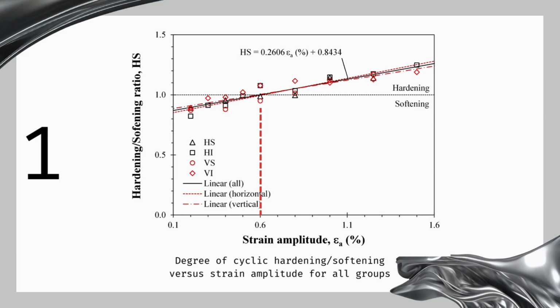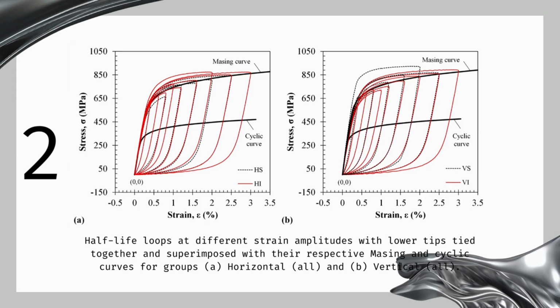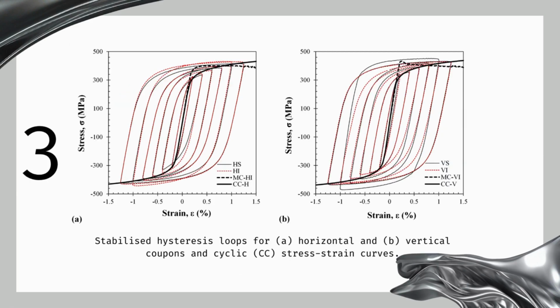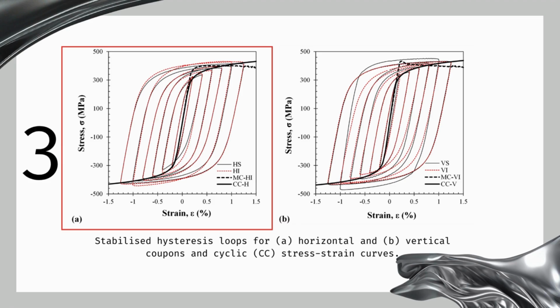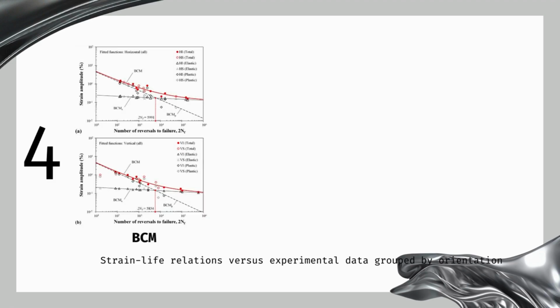We found a critical threshold at 0.6% strain amplitude, delineating the transition of a mixed cyclic behavior: cyclic hardening above and cyclic softening below. The material displayed a non-Masing behavior, likely due to changes in cell structure and dislocation arrangement. Orientation and through-thickness location exhibited minor influence on low cycle fatigue behavior, though slightly superior results were obtained from horizontal coupons.